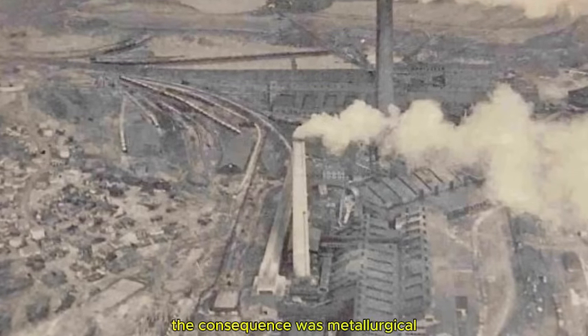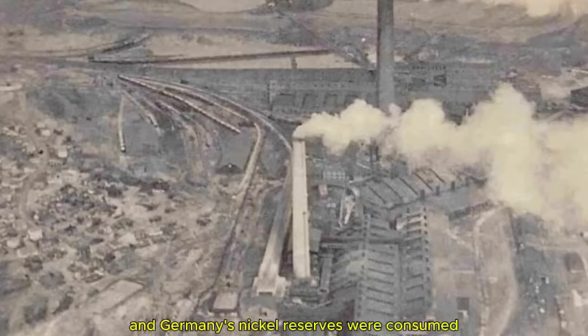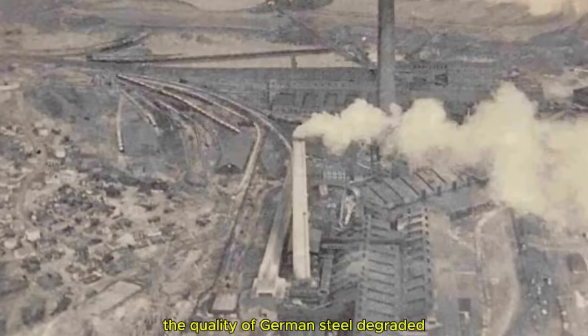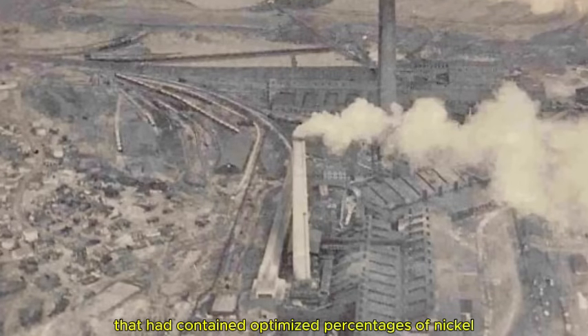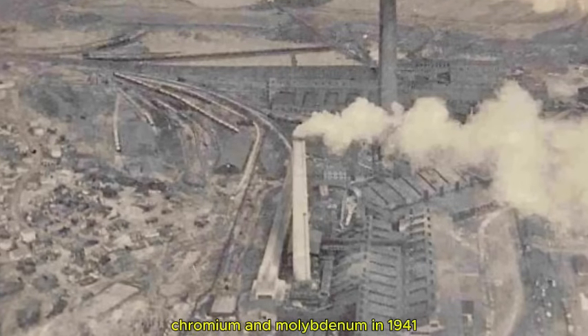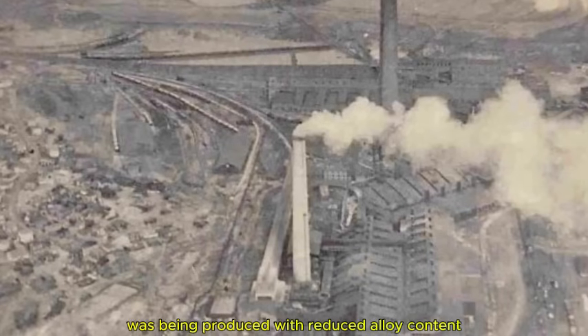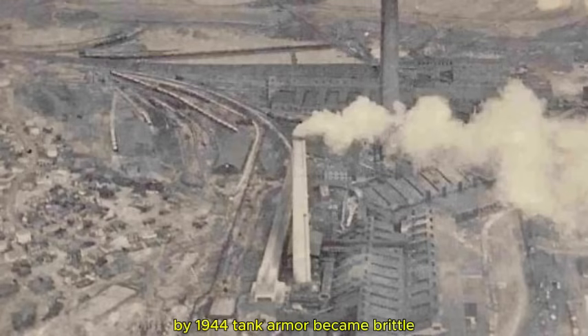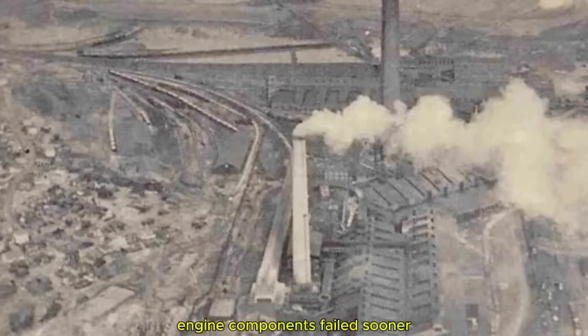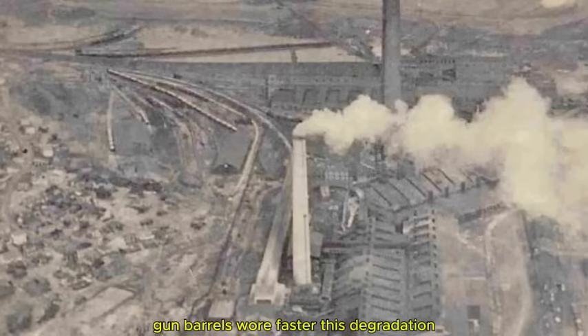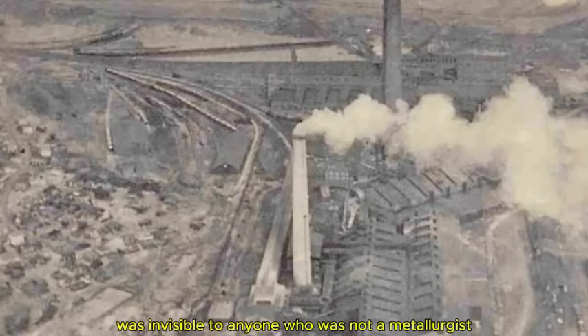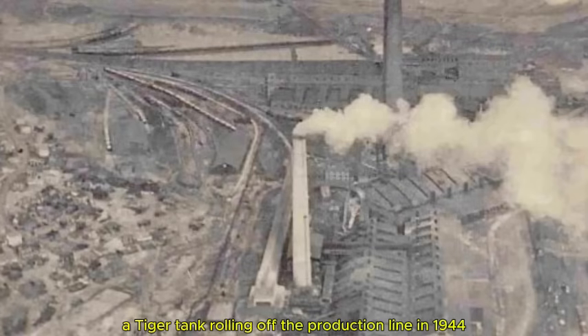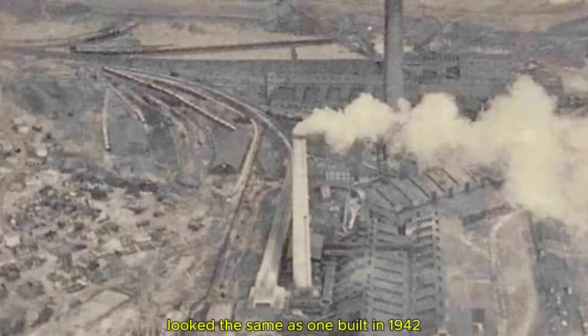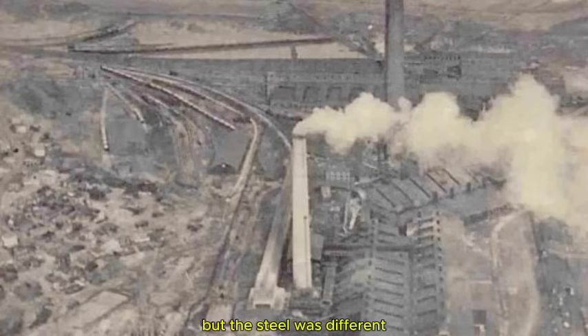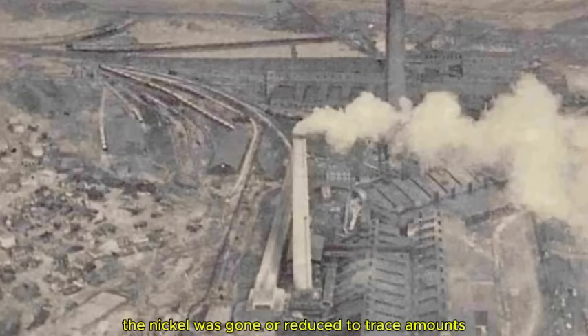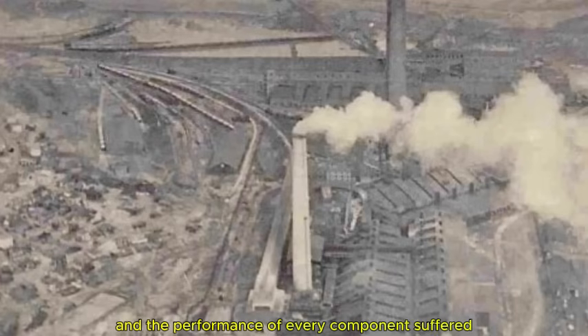The consequence was metallurgical. As the war progressed and Germany's nickel reserves were consumed, the quality of German steel degraded. Armor plate that had contained optimized percentages of nickel, chromium, and molybdenum in 1941 was being produced with reduced alloy content by 1944. Tank armor became brittle. Engine components failed sooner. Gun barrels wore faster. This degradation was invisible to anyone who was not a metallurgist. A Tiger tank rolling off the production line in 1944 looked the same as one built in 1942, but the steel was different. The nickel was gone, or reduced to trace amounts, and the performance of every component suffered accordingly.